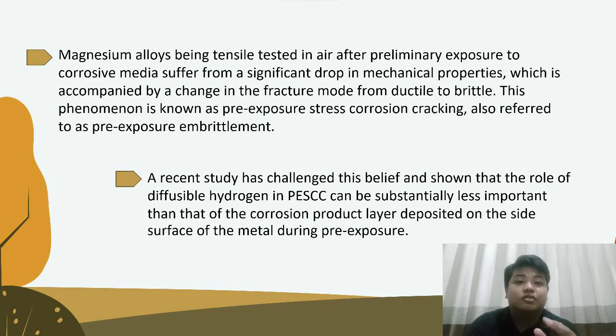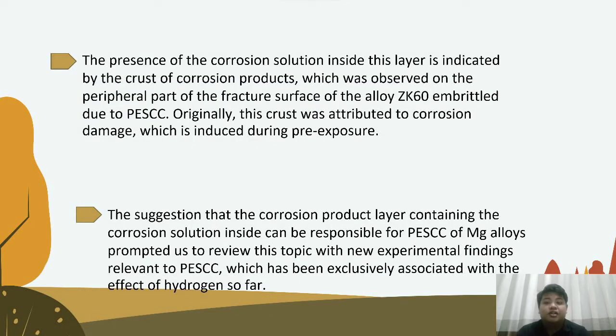Furthermore, a negligible concentration of diffusible hydrogen was found in the base metal of these alloys after the removal of the corrosion product. The presence of corrosion solution inside this layer is indicated by the crust of corrosion product, which was observed on the peripheral part of the fracture surface of the alloy ZK60 embrittled by PESCC. Originally, this crust was attributed to corrosion damage induced during pre-exposure. However, it was demonstrated that this corrosion product was formed not during the pre-exposure, but exactly during post-exposure mechanical testing in air. Two independent experimental observations corroborated this finding.